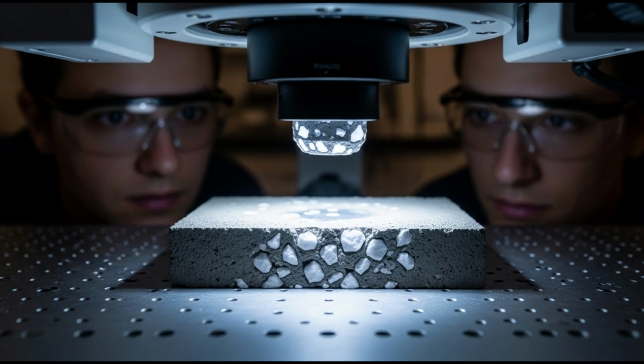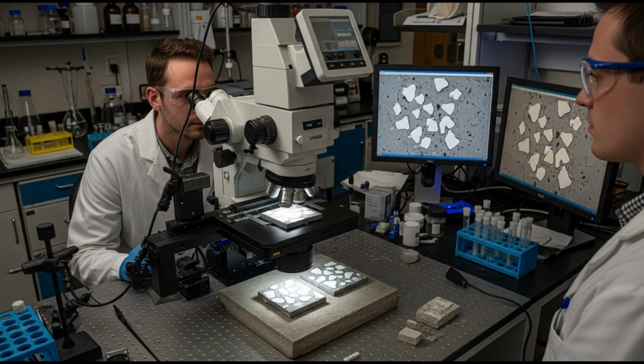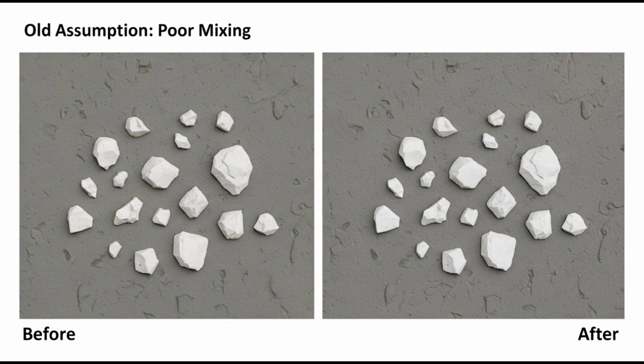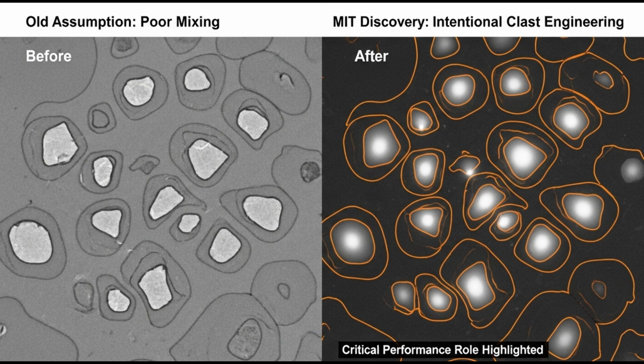MIT researchers publish findings from an analysis of Roman concrete samples using advanced imaging. They found something unexpected: small white chunks throughout the concrete, called lime clasts. For decades, these were considered evidence of poor mixing. Romans didn't mix their concrete well; lime lumps remained. The MIT team proved otherwise. Those lime clasts were intentional, critical to performance.